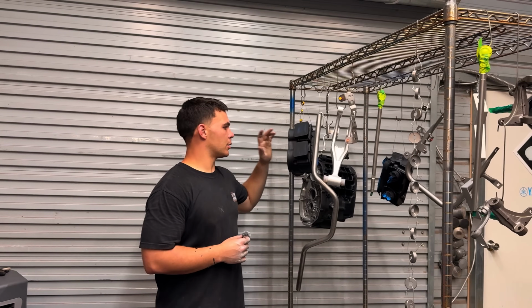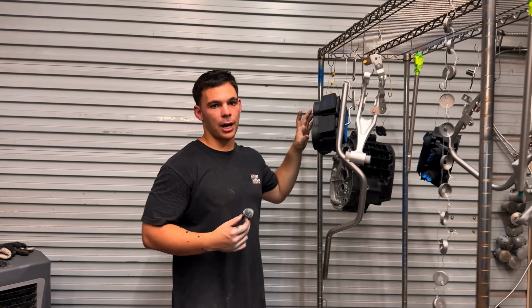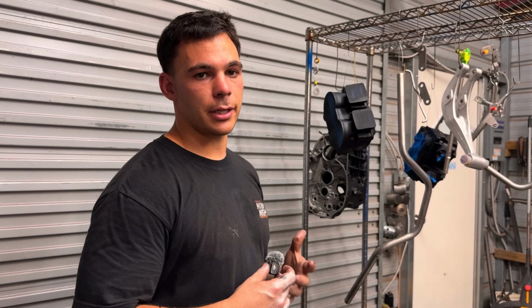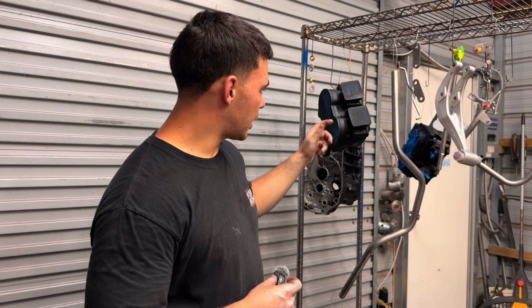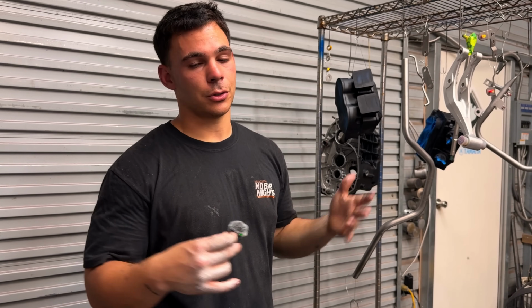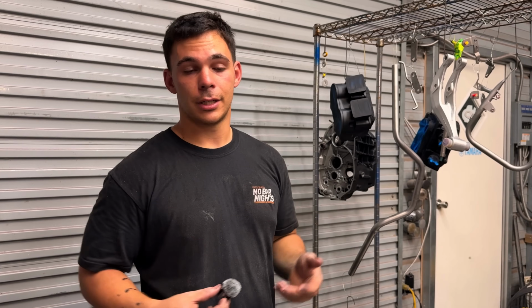We don't like to put our cylinders in the oven. We would powder coat these, I've done it before, but our experience is that it actually makes the nickel, which is the plating inside these cylinders, weaker. We coat at 400 degrees part temperature, so apparently it makes it softer, so we use an air cure Cerakote, and it almost looks like a satin black powder coat. It's still chemical resistant and all that.